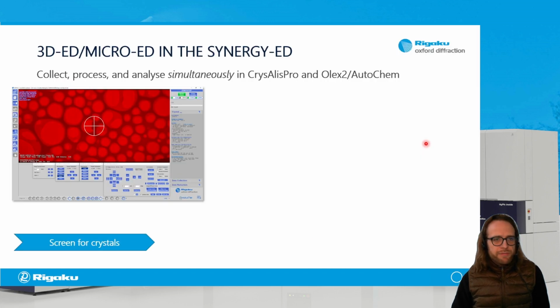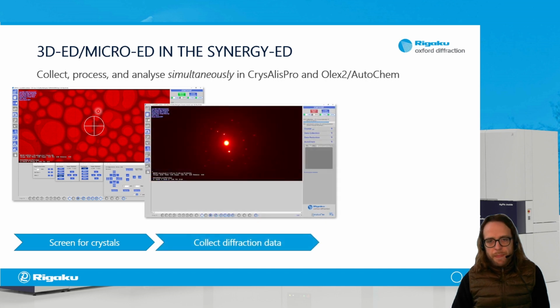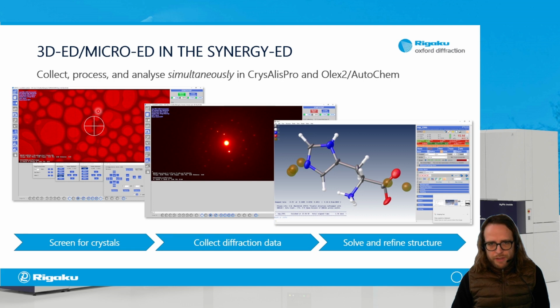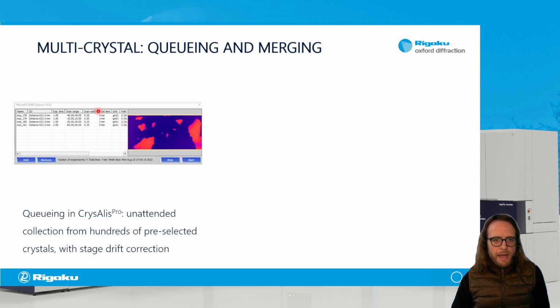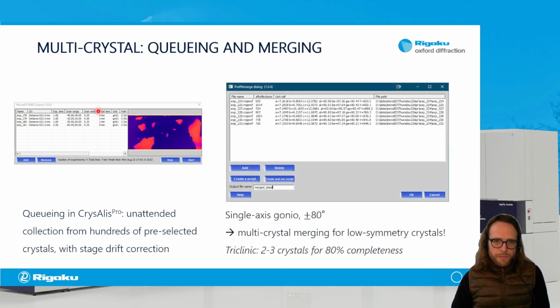So just very briefly, the workflow in a 3D ED experiment is that already inside Chrysalis Pro, you screen for crystals on your sample that you inserted into the vacuum, collect diffraction data, and then directly solve and refine the structure in OLEX or whatever software you prefer. We also have features built in there to have a queued data collection where you pre-select crystals for data collection on a sample grid which holds the different crystallites, and collect many data in an unattended way, and also to merge all of those into one data set to overcome this potential problem of low completeness arising from the single axis GONIO.